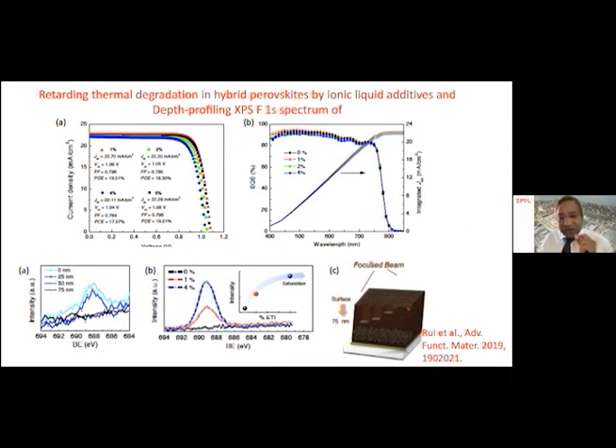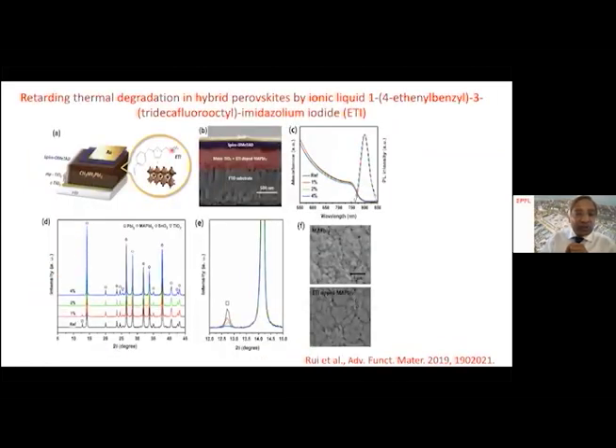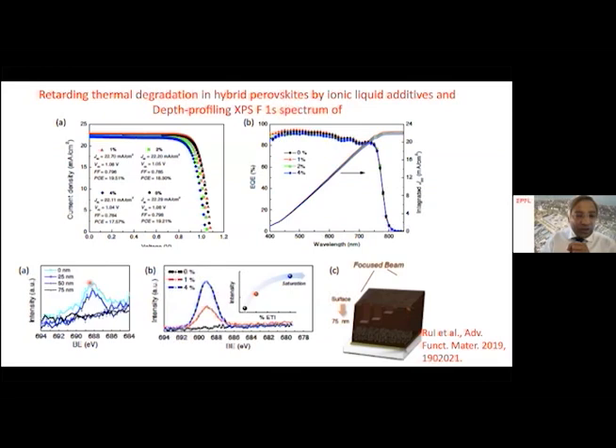So we did the XPS analysis by taking focused ion beam tunneling from one of these grains from top to bottom. And this is the fluorine binding energy as a guideline. So the 0%, you can see here, 1%, it gives this curve, and 4%, this is a guideline for the fluorine binding energy. So now what do you see in our perovskite grain? From digging from top to bottom at 0 nanometers, we do have a similar peak as shown here. That's coming from the fluorine. That's coming from the fluorinated ionic liquid shown here. This is the fluorinated ionic liquid. So now we go back, and the fluorinated ionic liquid at 0 nanometers and up to 25 nanometers, it's there. And then at 50 and 75 nanometers, it's disappeared.